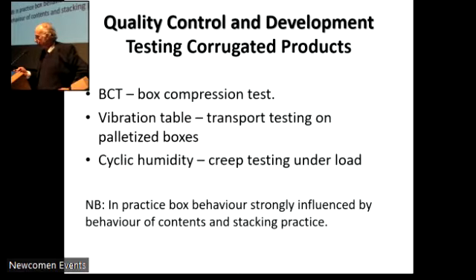We also test the box under different levels of humidity, because it must be said the weakness of any paper-based structure is its response to changes in its moisture content. And the real killer is where you're shipping in some parts of the world where you have a sharp change between climatic conditions during the day where it's hot and dry and climatic conditions during the night when it's cold and wet. So if you're going to ship from Southeast Asia to Europe, you're going to get a big variation in climatic conditions and big variations in moisture levels inside the container.